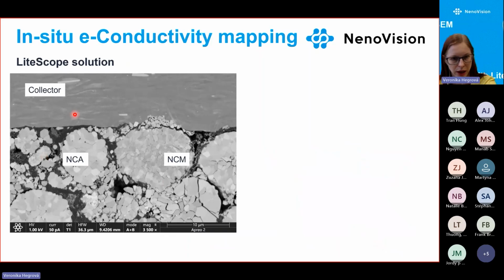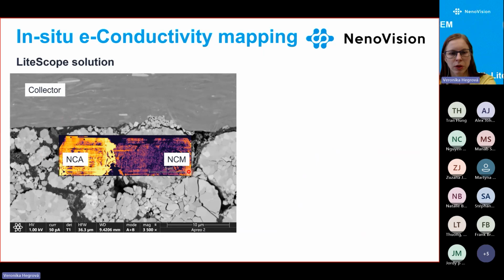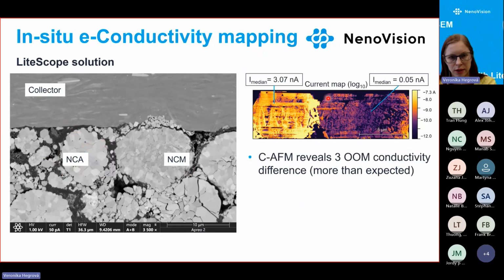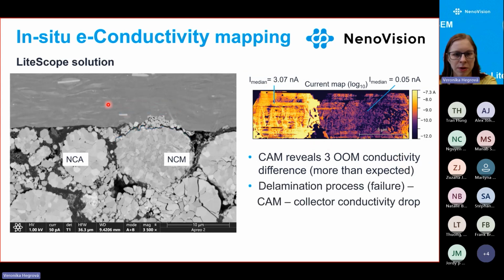As we identified the NCA and NCM parts, we measured the conductivity. And as we can see, one is much more conductive than the other. If we have a closer look, it's more than 3 orders of magnitude, which is much more than expected from just a different material. So we had a closer look at the SEM and see that there is a crack or delamination happening of the grain. So basically, this is probably the reason of the conductivity drop, that the collector is not fully connected with the grain.